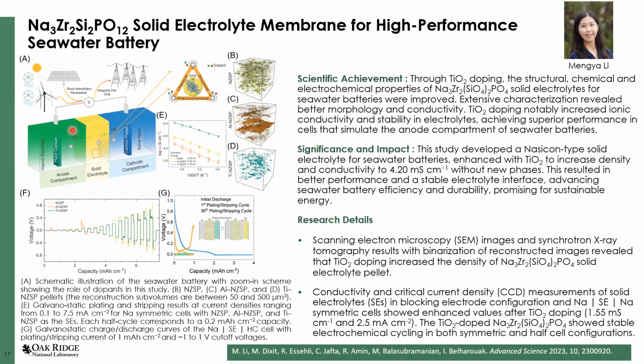So those are the kind of things. And this sort of device, because you can do it with seawater, should be relatively cheap and very useful for grid storage when it is developed completely. Of course, you have an organic electrolyte on one side and seawater on the other side. So these two things cannot mix. In order to do that, you have to have a membrane, which turns out to be a solid electrolyte membrane, through which you can transfer the ion.